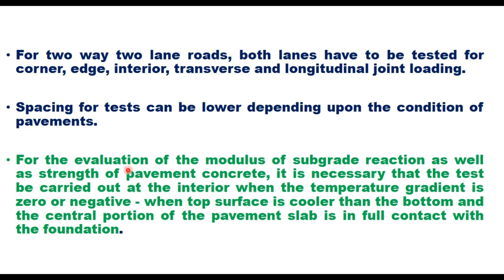Now for the evaluation of the modulus of subgrade reaction as well as the strength of pavement concrete, it is necessary that the test be carried out at the interior when the temperature gradient is zero or negative. That means when top surface is cooler than the bottom and the central portion of the pavement slab is in full contact with the foundation.